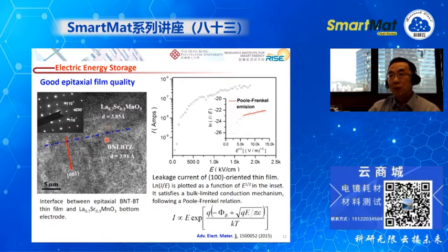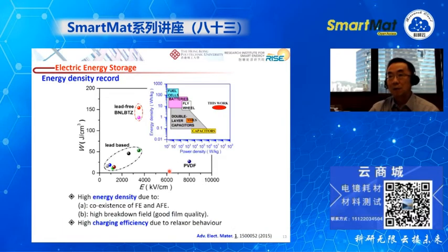That means the substrate and the film have a very good epitaxial relation. We also analyzed the leakage current as a function of the applied field, and found that the leakage current is controlled by the so-called bulk-limited conduction mechanism. Finally, we plot the energy density of our film in the Ragone plot. By comparing with other lead-based materials and the polymeric material PVDF, we found our energy density is very high.